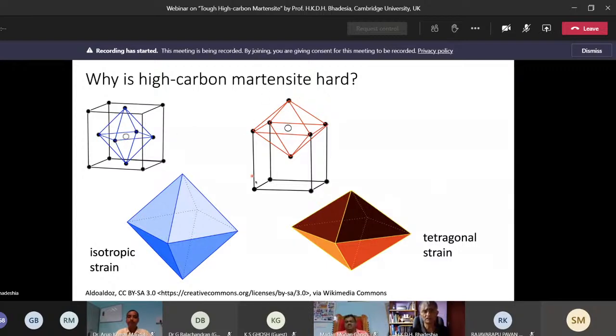Now consider this, which is body-centered cubic iron. These are the iron atoms, and this is the interstice for carbon atoms. Now this interstice looks like an octahedron, but actually this distance here is different from these distances here. So this is like a squashed version of the octahedral interstice in austenite. That means that when you put a carbon atom inside ferrite, it causes an anisotropic strain field, which has a huge interaction with dislocations. And that is the reason why carbon hardens martensite much more than it hardens the austenite.